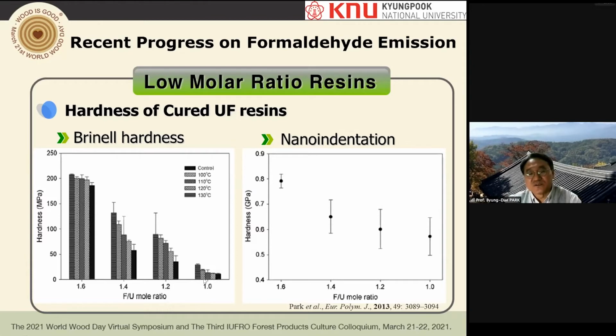Low molar ratio ones usually have lower hardness. And then we also did nanoindentation on the same films, and we have low hardness for the low molar ratios. That means when you have a low molar ratio, you have a low emission, but you have soft material at the end.